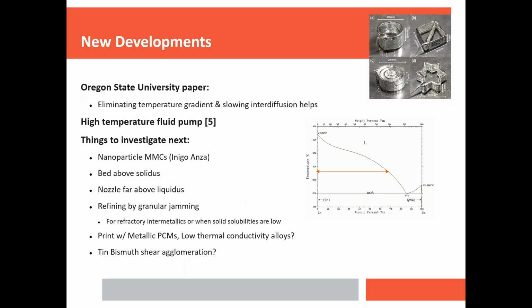The challenge that they forever face with that sort of system is unevenness of shrinkage of the part. You can address that to an extent by controlling the ovens very precisely, microwave heating, etc., directed to specific parts in the volume, careful temperature tracking. It takes a lot of engineering to address that problem, but it's still not necessarily perfectly solved. You can still have parts that slump, you can still have errors. And I guess at production scale, if you're printing 100 of these at a time, maybe some failure rate is fine. And it's viable. I mean, they're doing it.